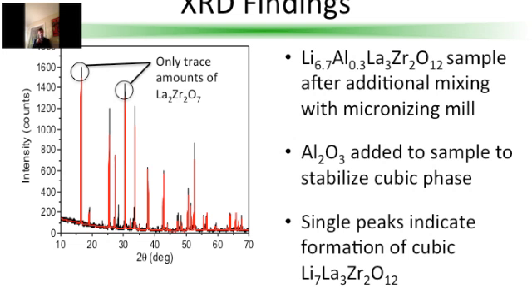As you can see from the X-ray diffraction pattern, the fitted model fits very well the experimental data, aside from a few unaccounted peaks, which are circled, that indicate the formation of trace amounts of lanthanum zirconate oxide.